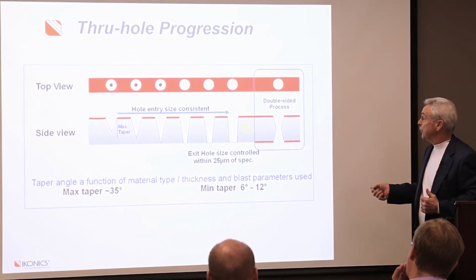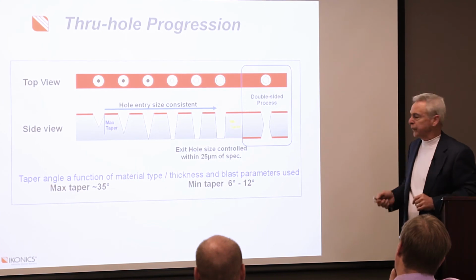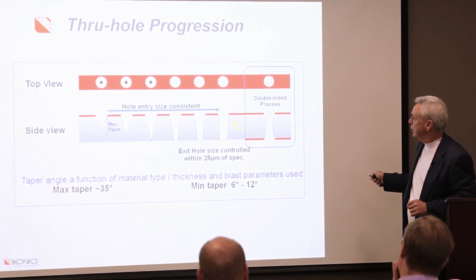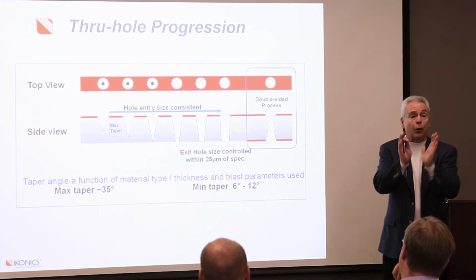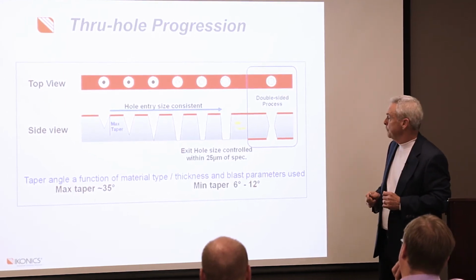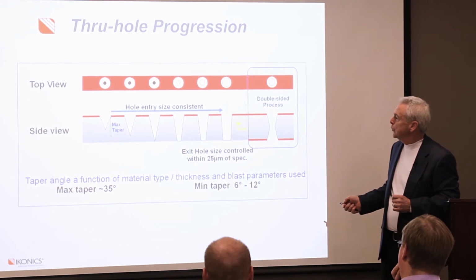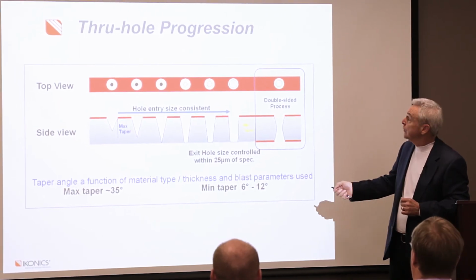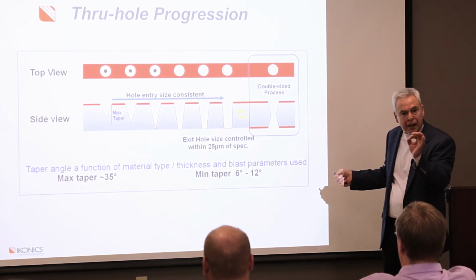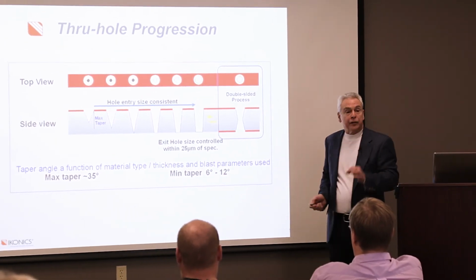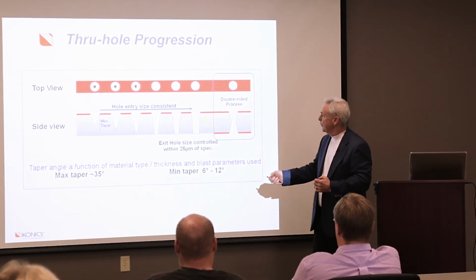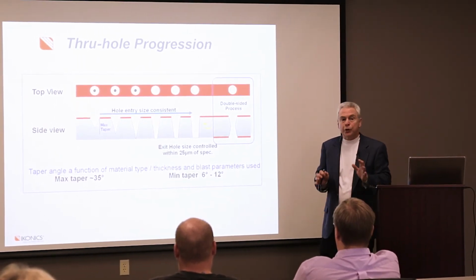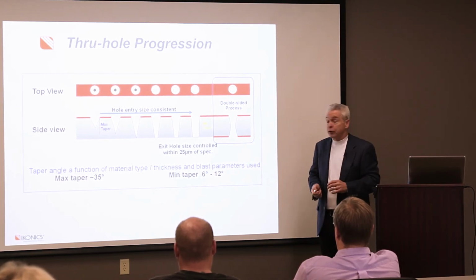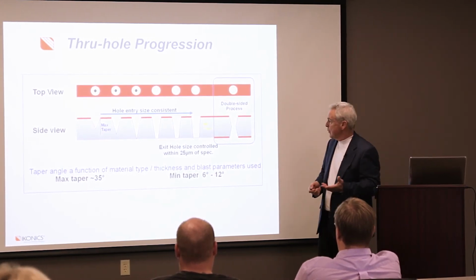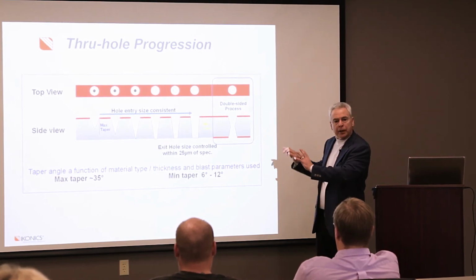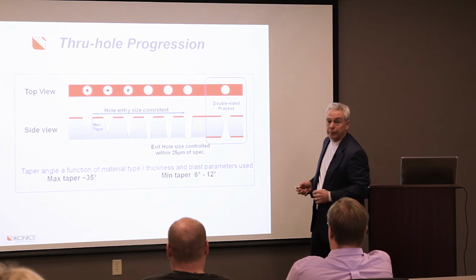And this is just showing in some applications, although not typically with composites, if you were doing this double-sided, you come down from each side and you end up with an hourglass effect. That's all that's showing. But the key point here is notice the entry hole is always the same because it's defined by the mask. So that entry hole diameter is always the same. The exit hole is something that can be controlled because you can stop at any one point, and you can control that pretty much within about 25 microns or about a mil of spec. So a little complicated, but that's the process, if you will, from beginning to end.